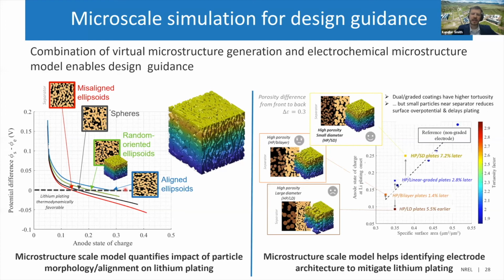And so he's plotted each of these. So this is the anode state of charge at onset of lithium plating, and he found that he had to normalize versus the specific surface area of each of these electrodes. In a lot of cases, the specific surface area was slightly different.